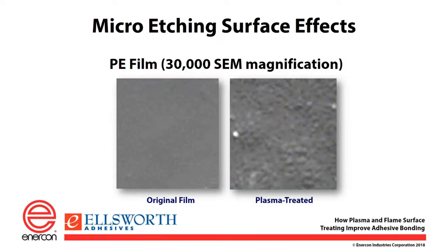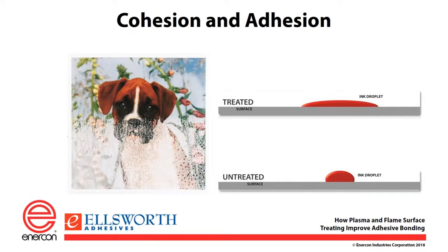This is a picture to show a PE film, the original film on the left, of course, and then after it's treated with plasma, you can see that it's roughed up on the edges over there, and again, you're increasing the surface energy, giving yourself more bond sites. This could be ink, it could be water, it could be anything, it could be adhesive. You've got the untreated surface down below. You could also say that that was a treated surface.